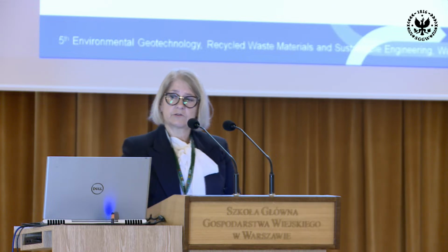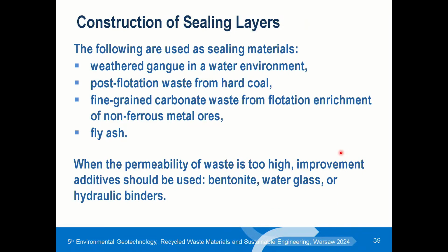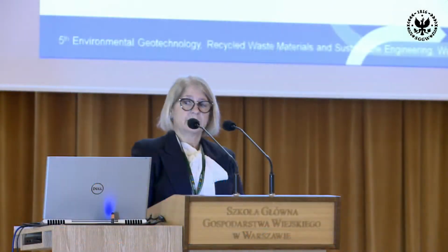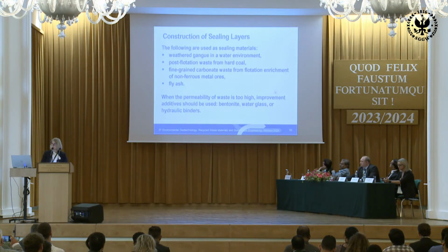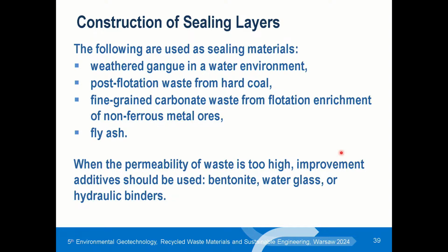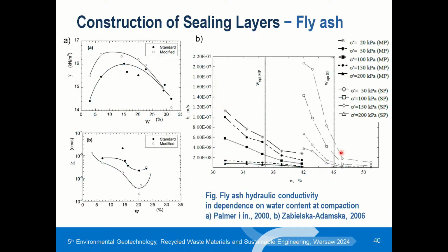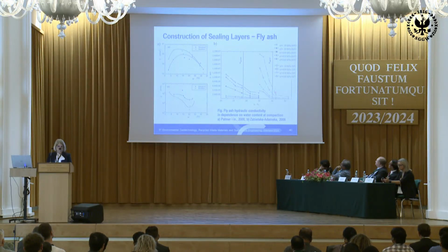Some words about construction of sealing layers, as for sealing layers can be used waste materials with very fine graining. It may be weathered gangue, in a water environment: post-flotation waste from hard coal, fine-grained carbonate waste from flotation enrichment of non-ferrous metal ores, and obviously fly ash. Fly ash can have a proper hydraulic conductivity to construct lining beneath the landfill.